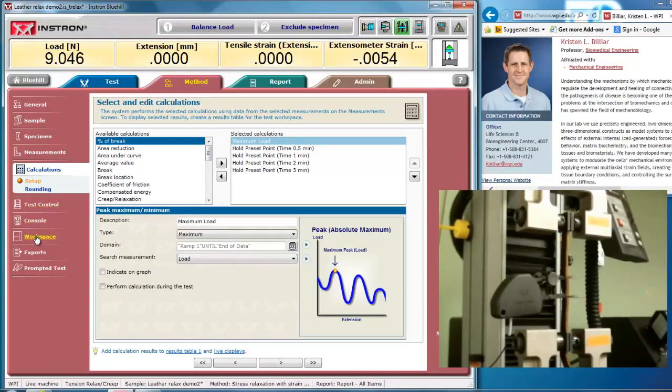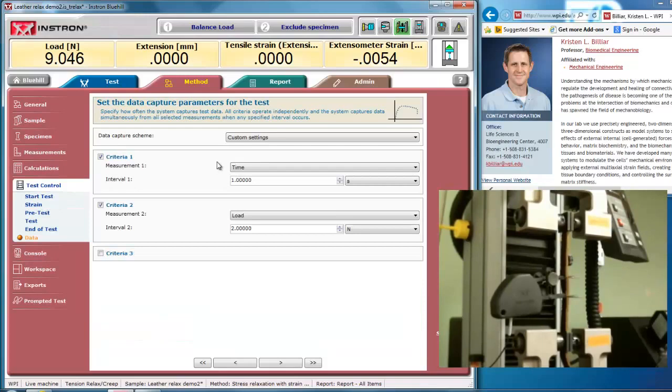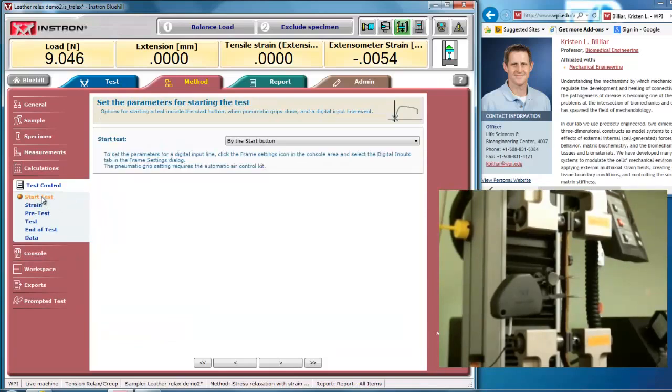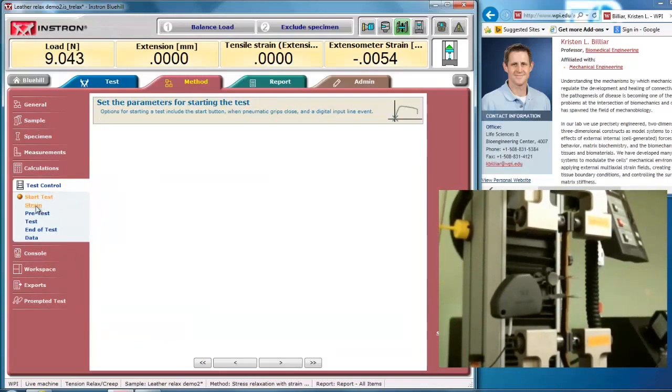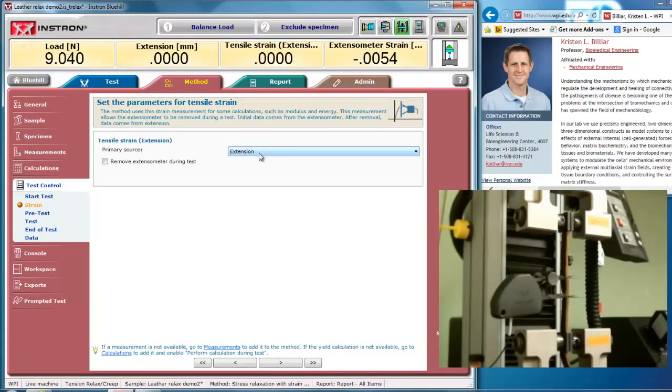Now I'm going to do test control. When I do the start of a test, it's by a start button, but by strain, now I not only can do extension control, but I can do extensometer strain. So I could run my test at, let's say, 1% strain per second using the actual local strain from the